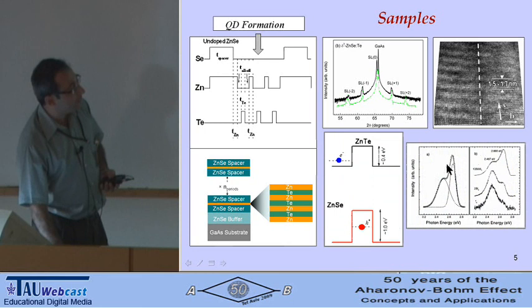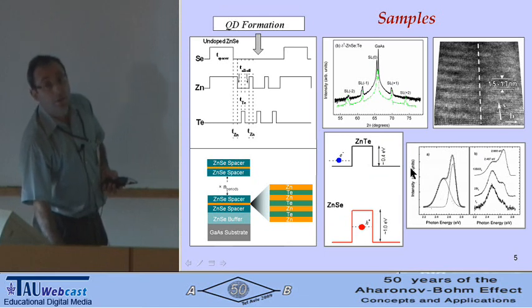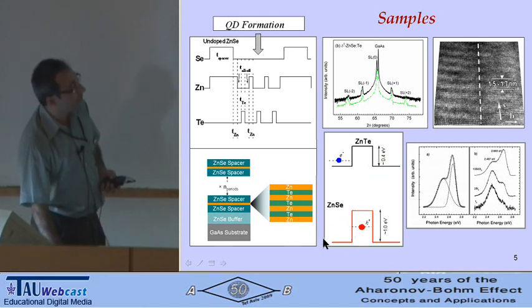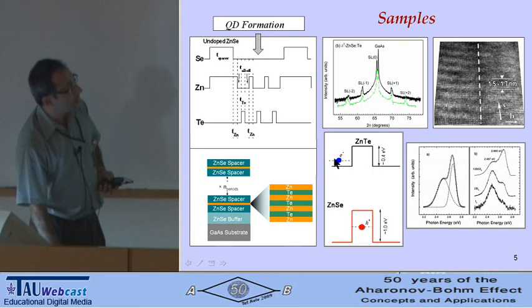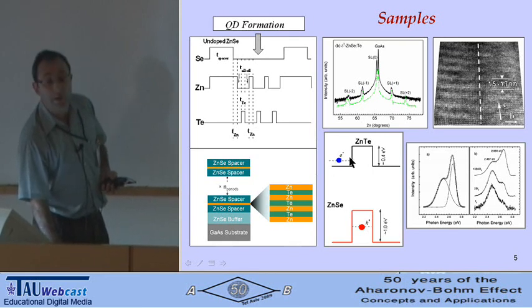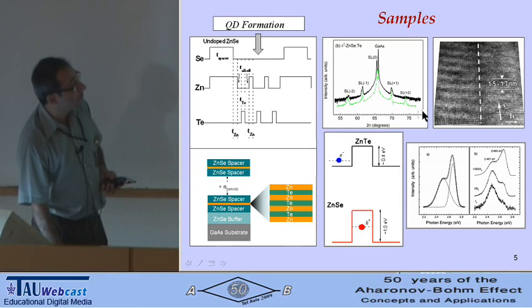So that's an optical emission, and what we will be concerned with is only this luminescence band, which is green. That's the band related to quantum dot emission. And that's the general band alignment for the zinc telluride, zinc selenide quantum dot at low temperatures. You can see that the hole is strongly confined in a very large 1 electron volt potential. And the electron is in the barrier, and it has a very high energy potential to penetrate into the dot. So it forms a perfect, very good